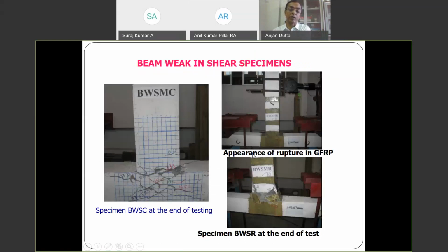And this is the kind of picture which you see after the failure. Again, you can see that the failure is a shear failure, and if you compare it with the flexural failure, you'll find that this is far more brittle in nature. And even when the retrofitted specimen was tested, the failure was also in a similar region.